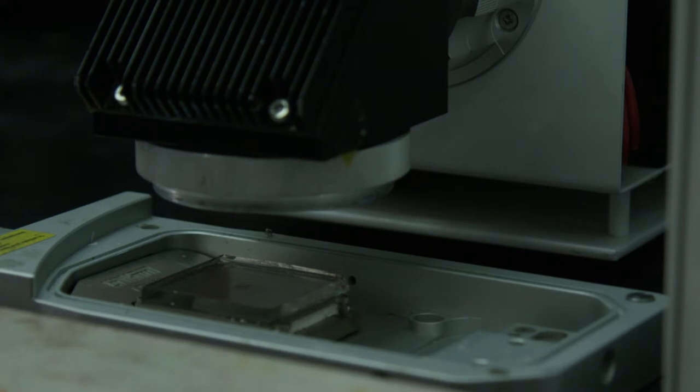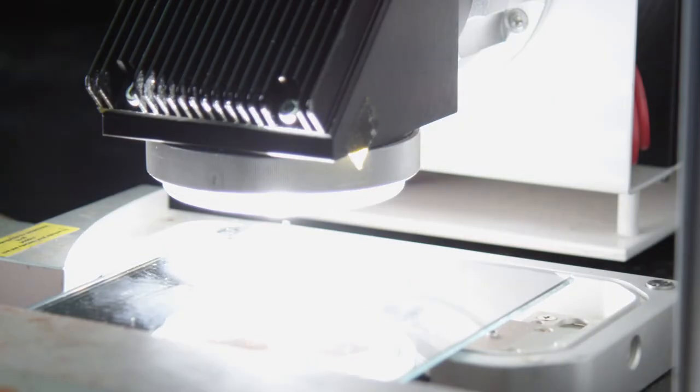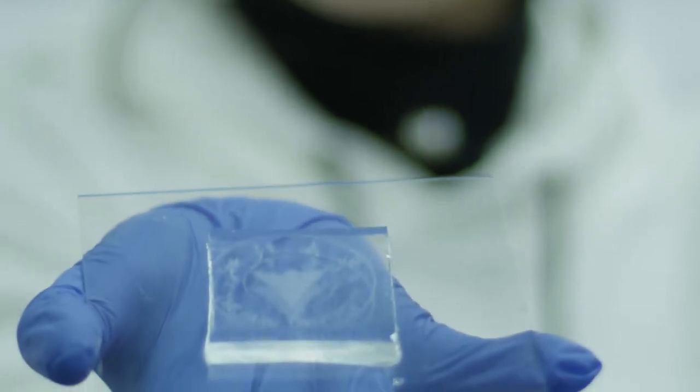First, they freeze the hydrogel totally, and then control the UV light spatially. Because the hydrogel has dynamic bonds, it will release the internal energy under the exposed UV light. So after we melt the hydrogel, the exposed area will return to the original state, and the other area will fix the pore state. So we can get the patterned porous hydrogel.